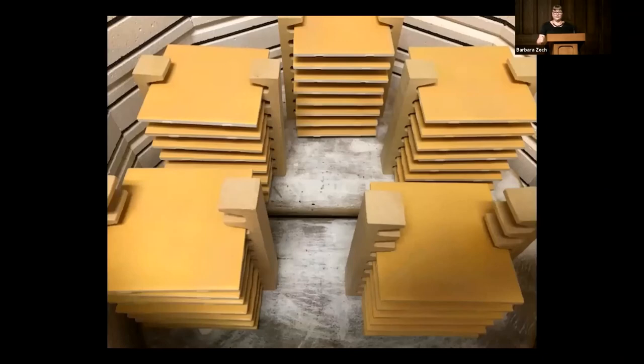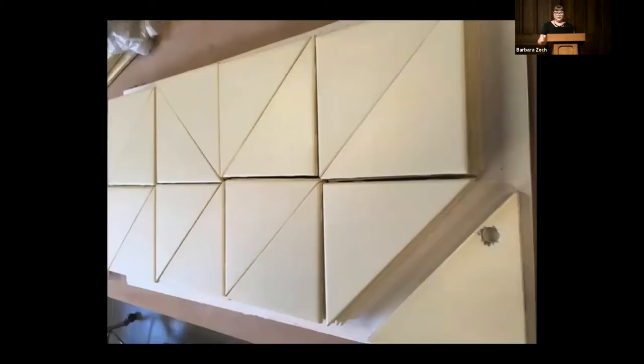Here are the yellow tiles in the large kiln — I had to create a total of about 200 of those, getting about 50 per kiln load. These are the ivory or white tiles, and there are about 100 triangles here. The triangles are literally a diagonal half of the six-inch tiles. Instead of glazing them and then cutting them on a wet saw, we decided to cut the tiles first so they had a nice, clean, crisp, glazed edge — when you cut a tile on even a wet saw, you can get little chips in the edges. So we got the bisque tile from Daltile, cut it on the wet saw, then glazed and fired it.